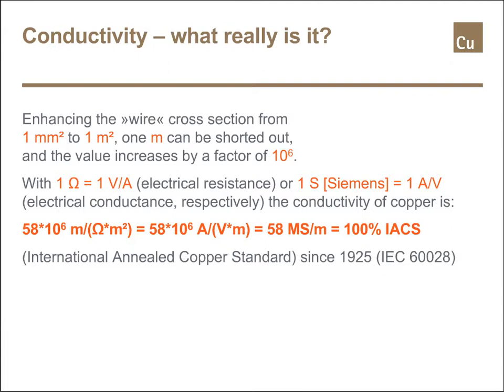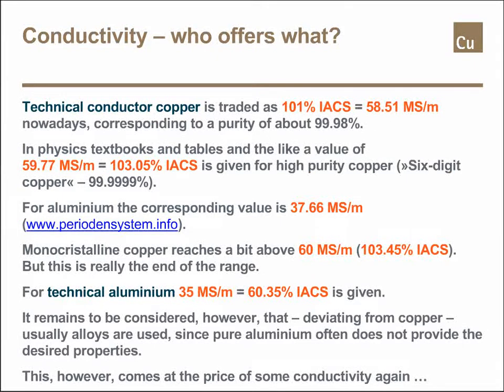This is the International Annealed Copper Standard, and this has been, so to say, defined as the rated conductivity of copper ever since 1925 in the IEC standard 60028. Now, technical conductors which you procure today will have a conductivity of about 101% IACS if made of copper, which is equal to 58.51 megasiemens per meter. This is reached when you have a purity of the copper of about 99.98%. As you will soon see, the purity of the conductor material is the crucial parameter for reaching a good conductivity.